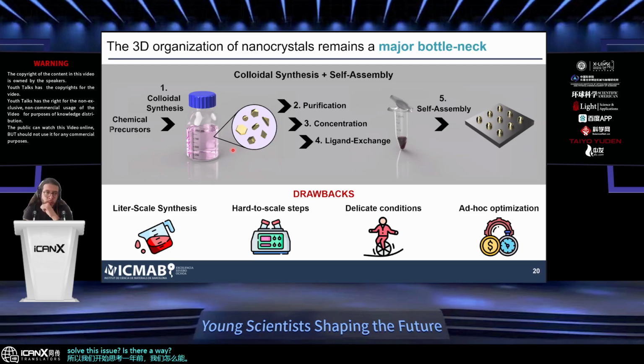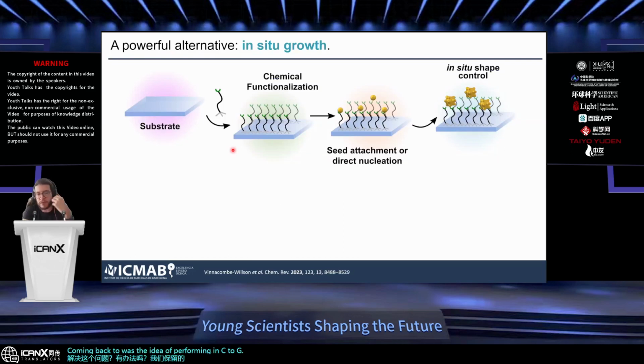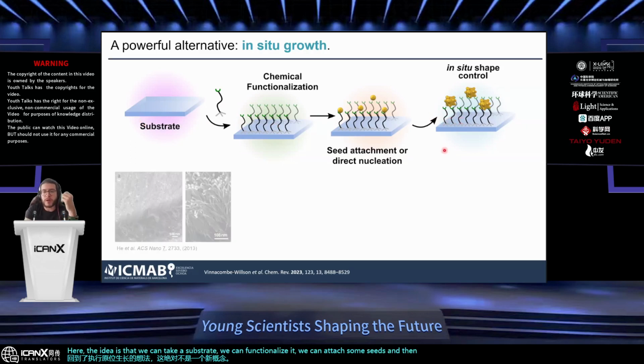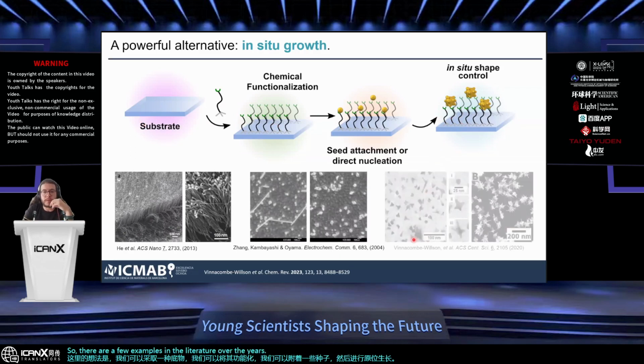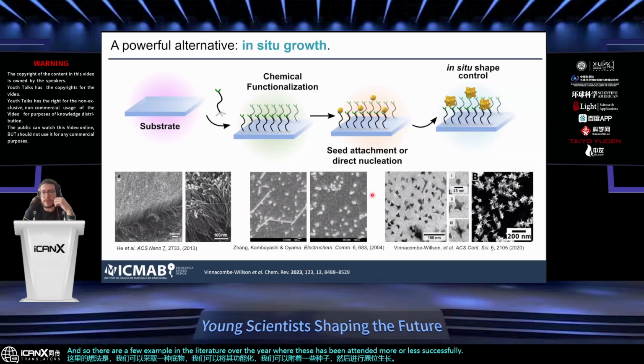Is there a way? And what we kept coming back to was the idea of performing in situ growth, which is definitely not a new concept. Here, the idea is that we can take a substrate, we can functionalize it, we can attach some seeds, and then perform an in situ growth. And so there are a few examples in the literature over the years where this has been attempted more or less successfully. But as you can see here, compared to the TEM images that I showed you at the beginning of the talk, the quality of the prepared structures is typically much lower, both in terms of size control and shape control. And so this has prevented this area of research from really growing in the same way that we observed for colloidal synthesis. So we started thinking about this and what was missing, what was the problem here.